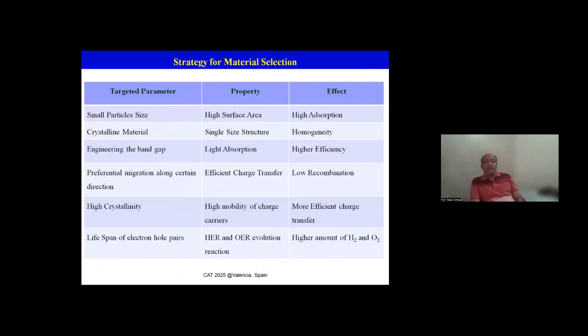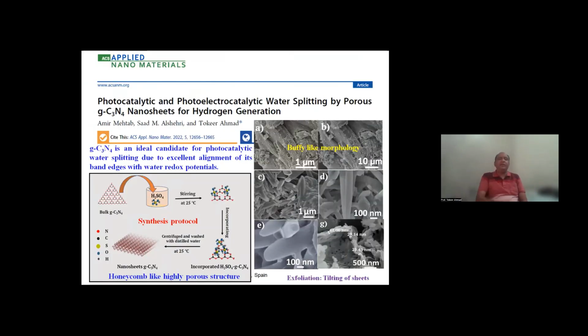So the strategy of the material selection is also important. You have to look at what kind of effects you are interested in, what kind of properties you must look for, and what should be your target parameter. For example, if you are really interested in high hydrogen and oxygen amount, then you have to look for the lifespan of the electron hole pair. For efficient charge transfer, you should look for the high mobility of the charge carrier. Then crystallinity becomes very important for homogeneity and high adsorption; the crystallinity as well as the small particle size are the important target parameters. So accordingly, you can fix your mind and then go for their properties and other kinds of application. So in this series,